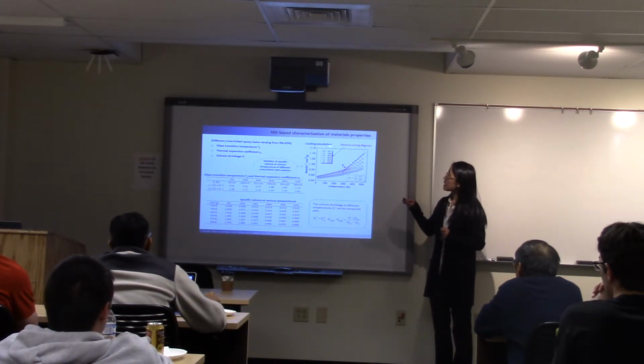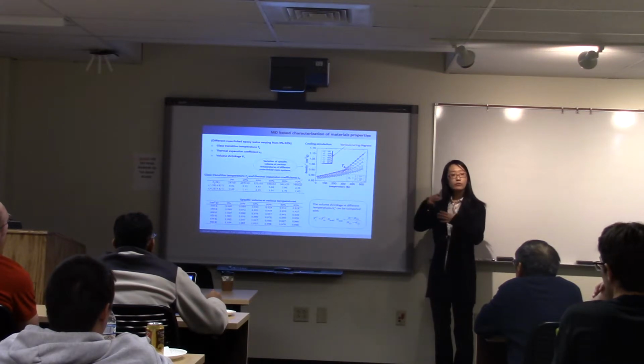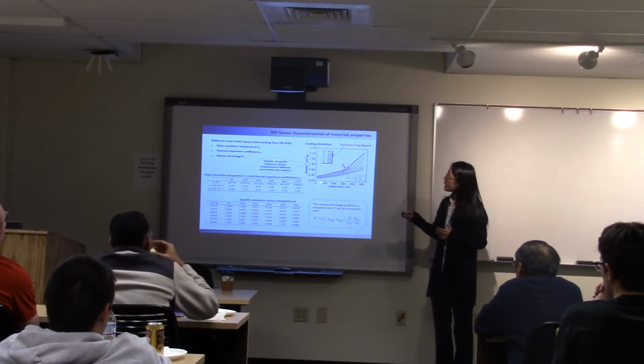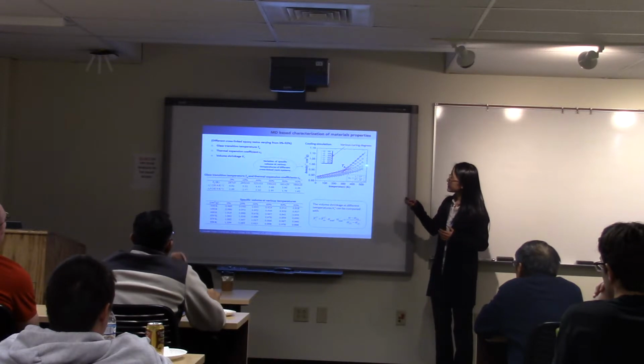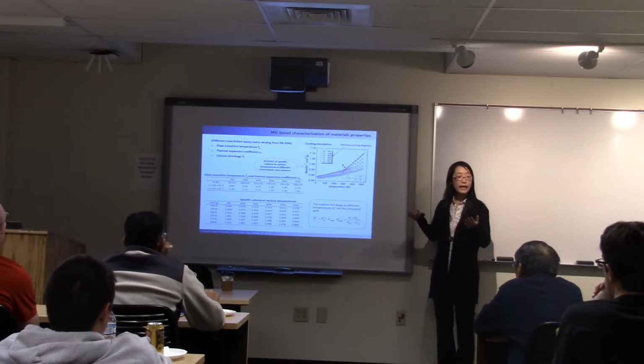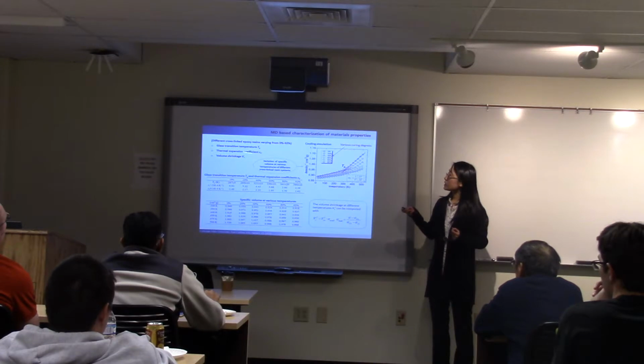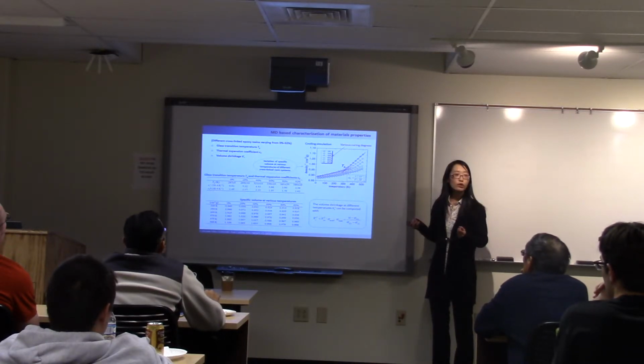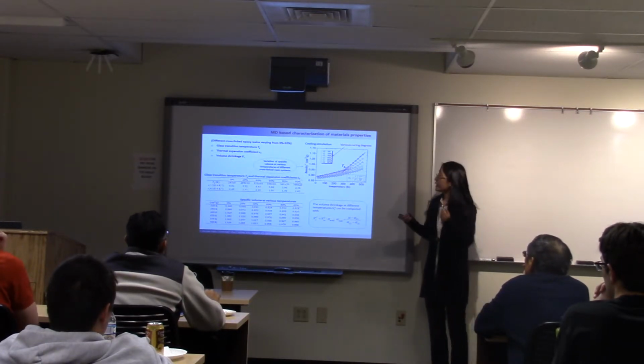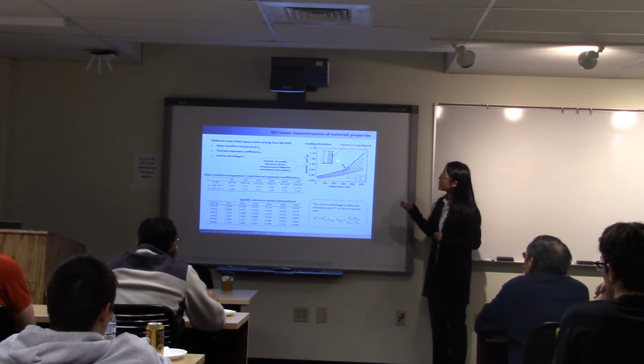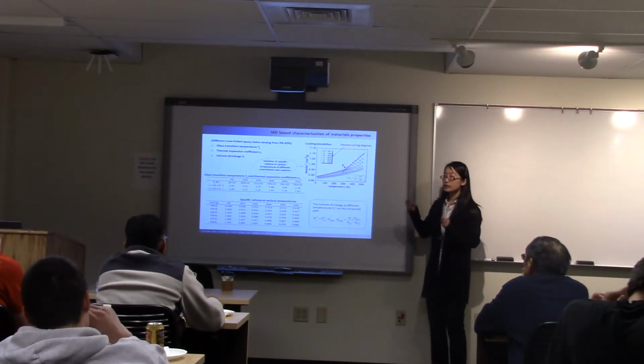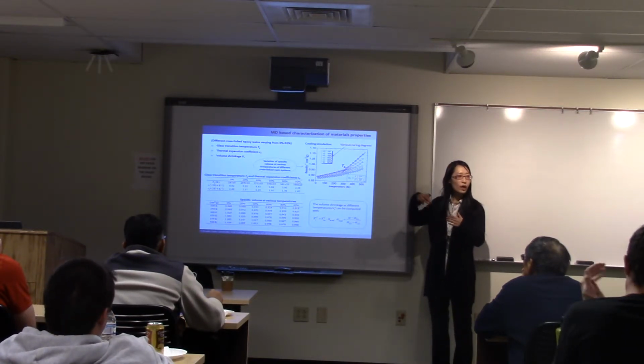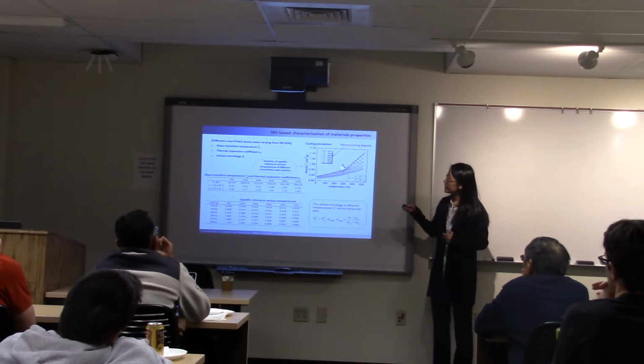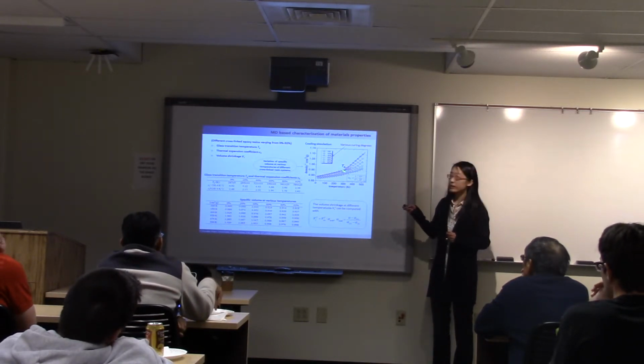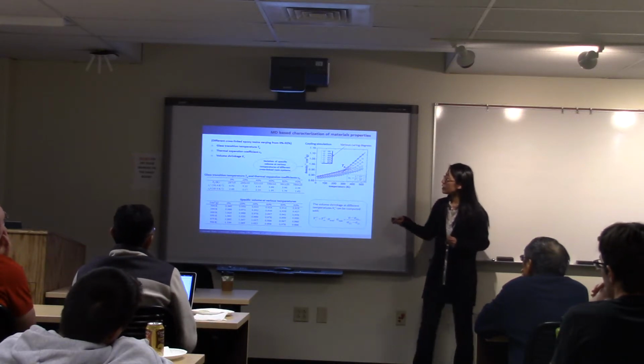We first do a cooling simulation that gradually brings down the temperature of the whole system and measure the density. The curve is given here. From this plot, we can get a lot of information, such as the glass transition temperature, the thermal expansion coefficient, as well as the volume shrinkage. We first see how to get the glass transition temperature. We do linear fitting to this curve, and we will see a transition in the slope of the fitting line. This intersection is the Tg, giving an indication of the glass transition temperature.